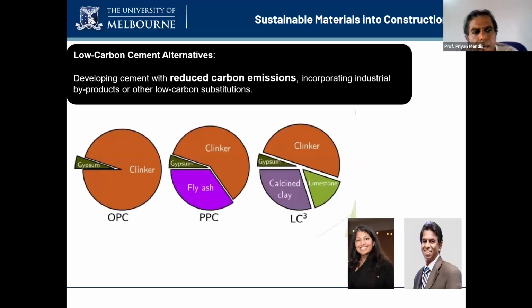So the other one, as I mentioned, is an innovation. Naturally, I'd give a lot of credit to Karen Scrivener in Zurich for coming up with LC3, a low carbon material. This is something we can do with ordinary Portland cement, with the fly ashes and all that, mixed in blended cement. You can buy blended cements here now, but what we're doing is adding limestone, and then calcined clay.